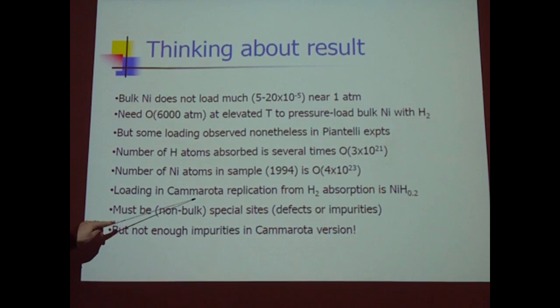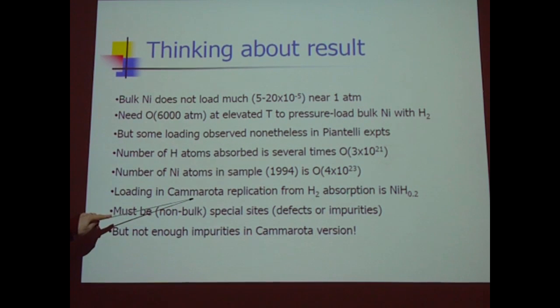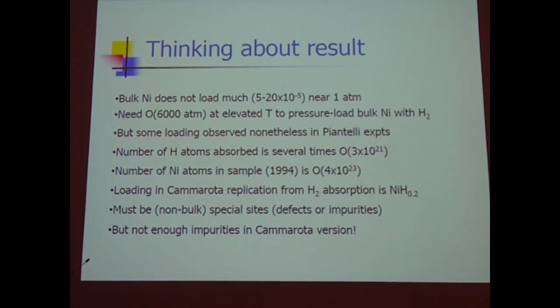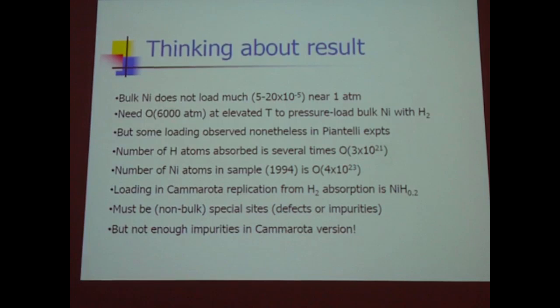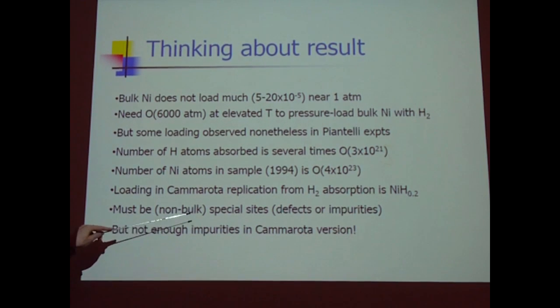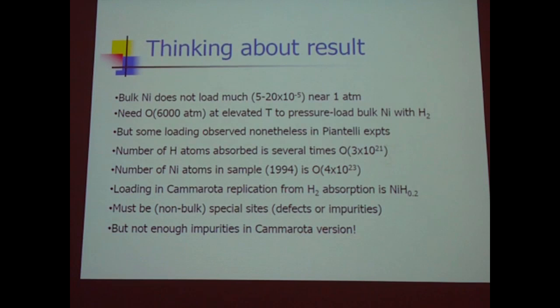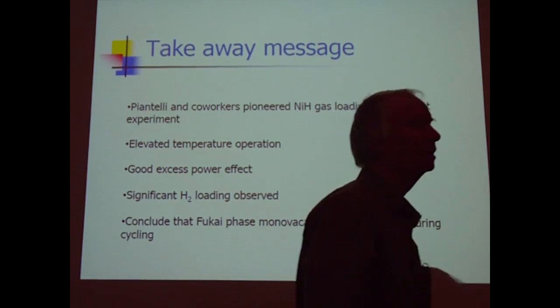In a paper by Cammarota and colleagues, who basically looked at the same system, they cycled it lots of times. They got a loading up to 0.2, nickel hydrogen 0.2, so 20% loading. And these numbers are phenomenally large. If you look at this, you just can't be anything other than astonished. So it has to be non-bulk loading, which means there's special sites, which means defects or impurities. Now, if you're going through the cycling, you're cycling hydrogen in and out, does that introduce impurities that make it into the nickel? I didn't think so. I thought defects. So not enough impurities in any event for the Cammarota. But did the lattice expand in this? We don't know.